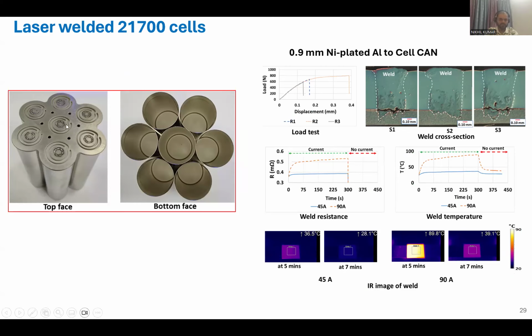And I welded the bus bar to the can material successfully. Initially the trial is done on the can. Once I was satisfied there was no bottom sheet penetration, I implemented the parameters on the actual bus bar and the actual cell. These are the tests I did for the cans. There is no bottom sheet penetration, but there are cracks because these are two dissimilar materials, aluminum and steel. And this is the lap shear test for three repetitions.